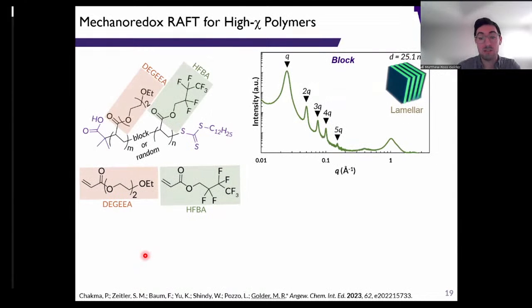A polymer science way of assessing the microstructure of these materials, and proving that we actually have a block of hydrophilic building block and then a block of fluorinated building block, is to use a technique called small angle X-ray scattering. Because these are highly immiscible, we would expect these to phase separate in the bulk, and it's known that they'll form well-ordered nanostructures, and we can probe that with SAXS. And that's exactly what's shown here on the top right. It's shown that these materials self-assemble into well-defined lamellae.